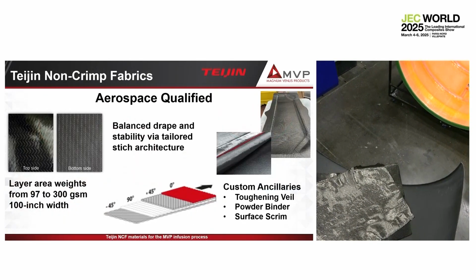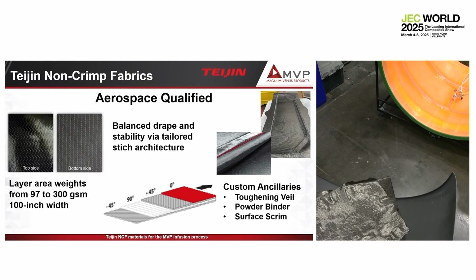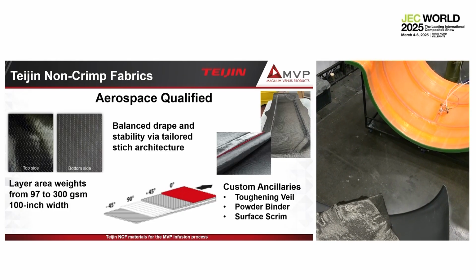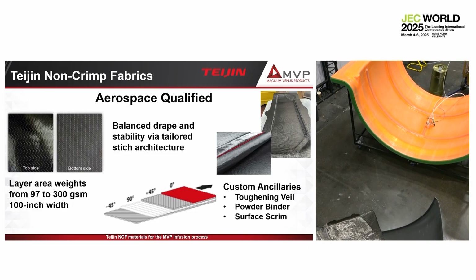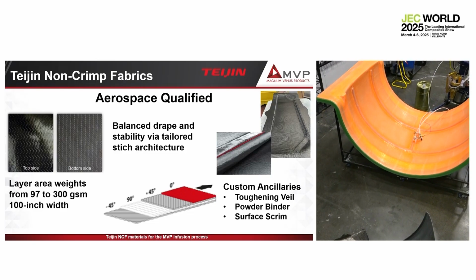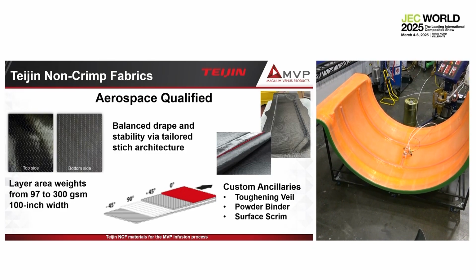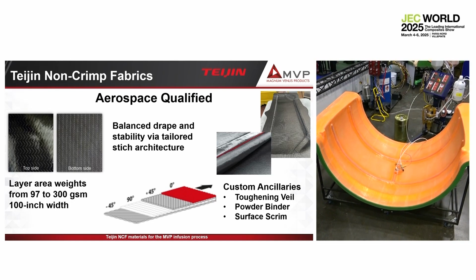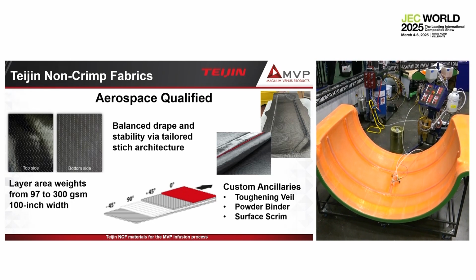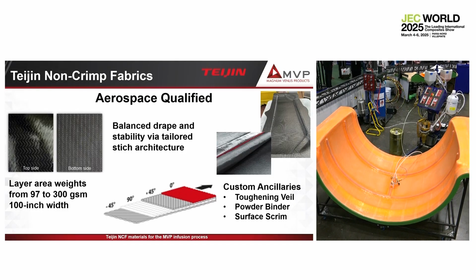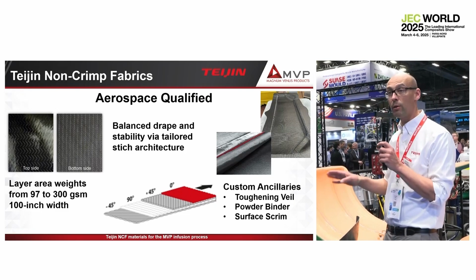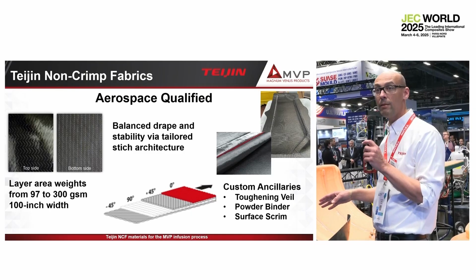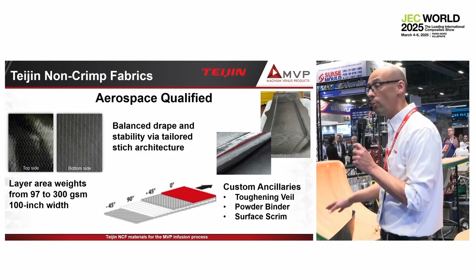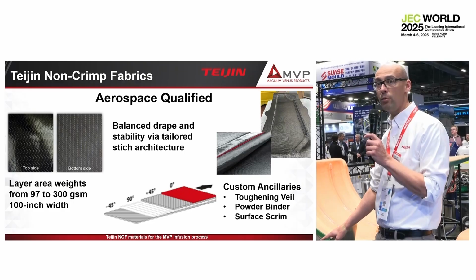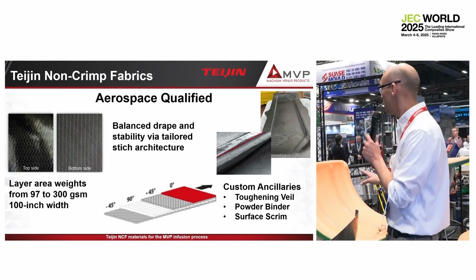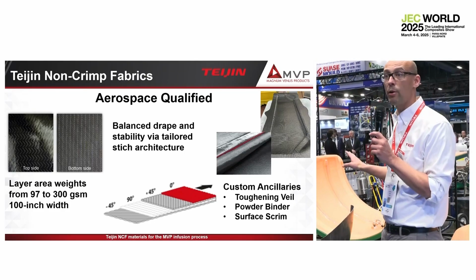Charles mentioned the grooves from MVP. This is a process only from MVP, and why we want to work with them, because they can design this membrane for the preform reinforcement and the resin that you're using. Now, in this case, it's too high viscosity. We cannot get that high fiber volume. But if we are looking at an aerospace grade epoxy with the appropriate viscosity, we can easily achieve 58 to 60% fiber volume. That, as I know, is really unheard of in this process.